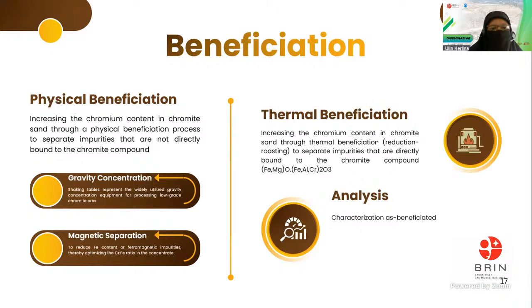I use a shaking table to separate the impurities from the mass of the material, and then I do the magnetic separation to reduce the Fe content or ferromagnetic impurities that are not directly bound to the chromite compound. The optimal result of this physical beneficiation is followed by the thermal beneficiation. It uses a reduction roasting process to separate impurities that are directly bound to the chromite compound. And then the last is analysis. What is the product of the beneficiation?